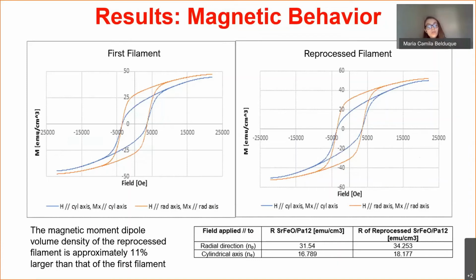Additionally, the remanence of the strontium ferrite nylon 12 composites when the field is applied parallel to the radial direction is 31.54 EMU per centimeter cubed, and 16.789 EMU per centimeter cubed when the field is applied parallel to the cylindrical axis. So, although the reprocessed filament has a higher remanence in both directions, which are 34 EMU per centimeter cubed and 18 EMU per centimeter cubed, these are not significant increase values. We can observe, however, that the remanence is always higher when the field is applied parallel to the radial direction.